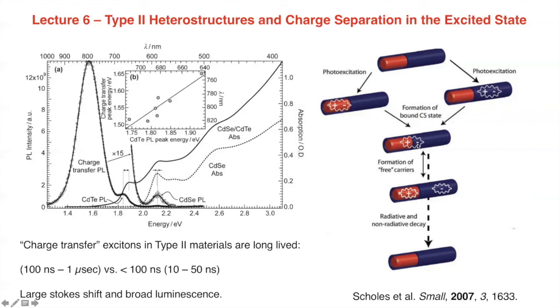Okay, and so the radiative recombination from this structure depends upon the strength of this interaction, the degree to which the charges overlap, and the concentration of this bound state from which the photoluminescence process happens. And so the temperature dependence of this luminescence reflects that higher temperatures reduce the recombination probability for this reason.